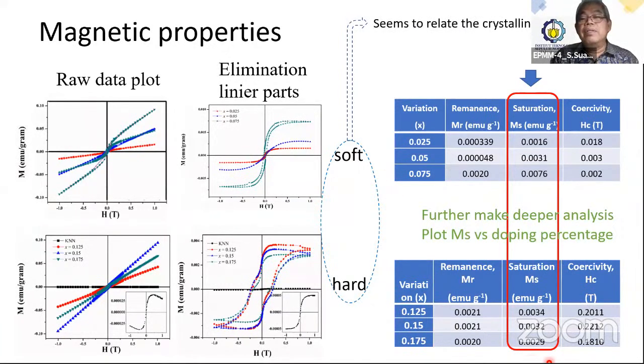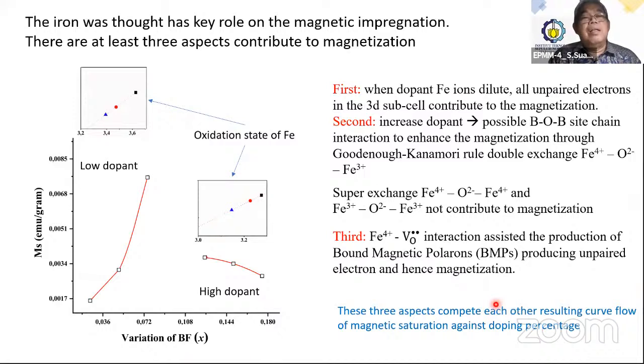This table shows you the numerical values of hysteresis variables. For the analysis, by taking the saturations MS and plotting against the X, we can construct the MS-X relationship. The iron was thought to have key roles on the magnetic impregnations.